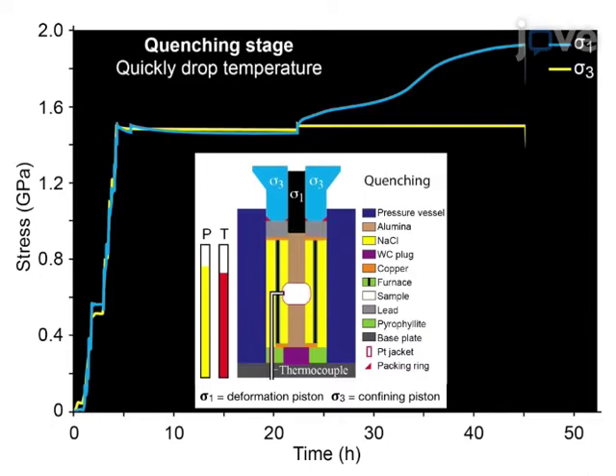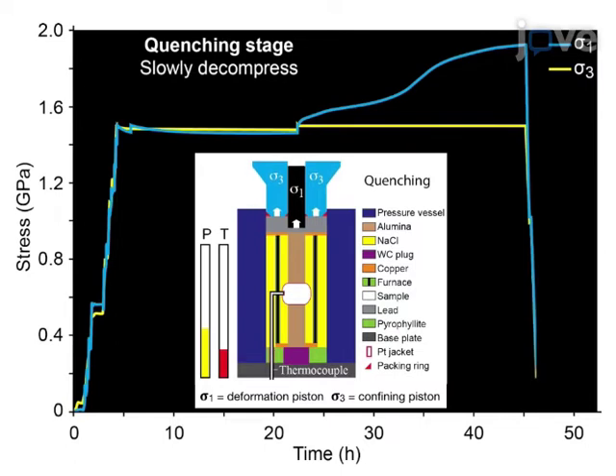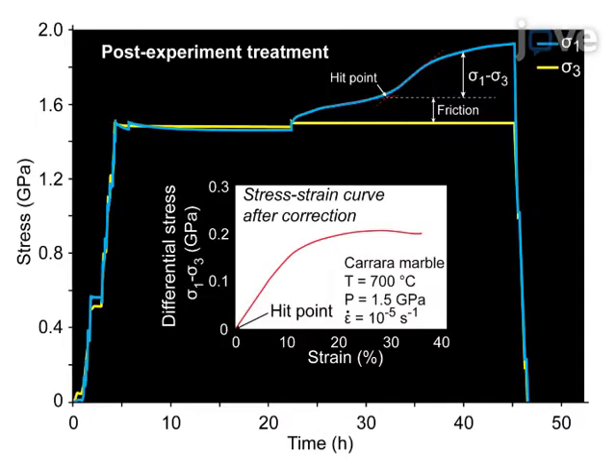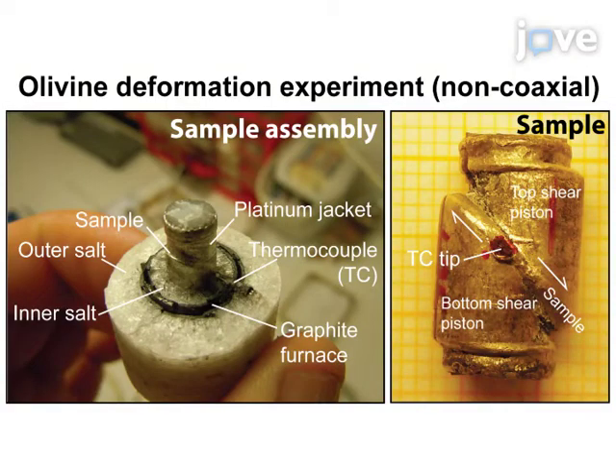When deformation is stopped, the temperature is quickly dropped and the pistons are moved back, so that pressure is slowly decreased to preserve microstructures. After the experiment, the stress versus time curve is corrected from friction and rig stiffness to calculate the total strain and differential stress prior to characterization by analytical techniques. This type of experiment can also be performed with non-coaxial geometry, as shown here, for an olivine aggregate deformed at 900 degrees Celsius and 1.2 gigapascals.